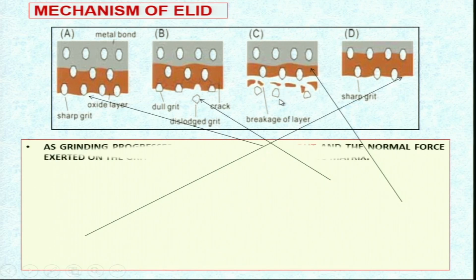Now, you can see here in the second slide, wherever the oxide layer becomes weak and there is a large force on the abrasive particles, they detach from the bonding material and separate out. So, you can see here the crack being formed over here, dislodged grit over here, and these are the dull grits. These are the sharp grits, but these are the dull grits, and once they become dull, the force that is acting becomes larger compared to the one which is acting over here. As a result of that, these abrasive particles dislodge, and further you can see breakage of the layer, dislodging of the abrasive particles, and this becomes the thinner oxide layer, and once it is thinner, further processing takes place, as we will see here.